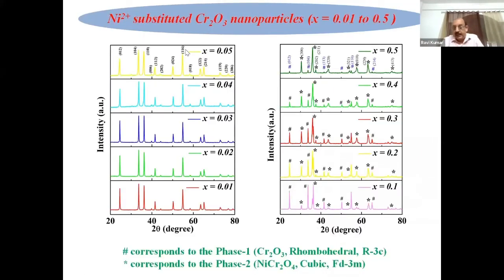Now you come to the nickel. Nickel is playing a different role. Here we learned a lot in this experiment. First, when we have a low concentration, 0.05x, they all are showing a single phase. As soon as we go to 10% and above, there is a mixed phase. So you have a phase 1, which is a rhombohedral phase.